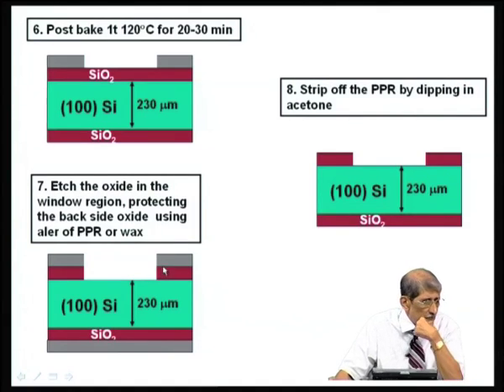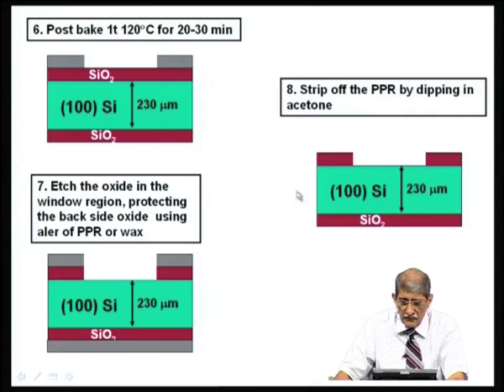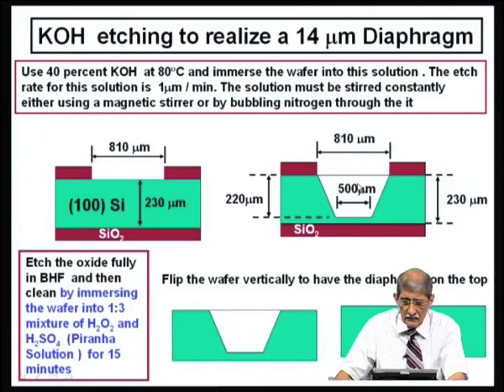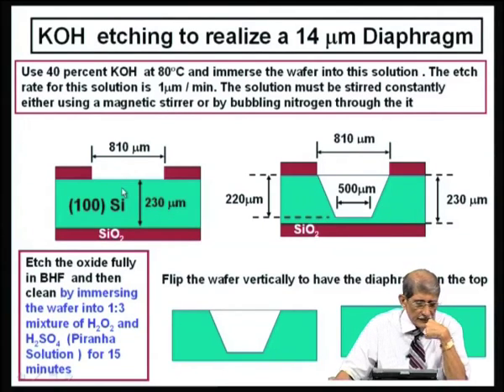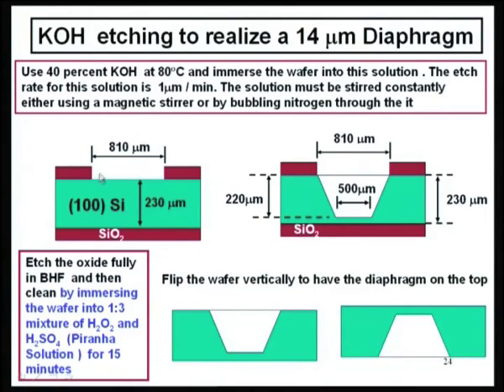Then, once you etch this oxide, strip off the photoresist from both sides. So, starting from the oxide all over, you have ended up with the oxide removed from here. Now, this one you put in the potassium hydroxide etchant. So, in this portion you can etch silicon, and from your knowledge of this KOH etching you will see that it will go in this direction, controlled by the 111 plane.